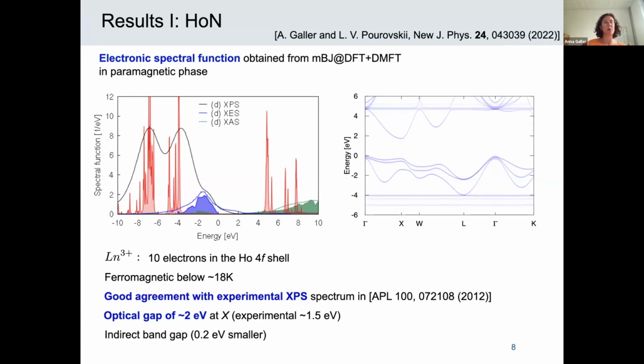So what I can compare here is only the peak position, because in my simulations, I don't really simulate a photoemission experiment, so I don't have any photoemission matrix elements in my simulations. And I should also point out that we also nicely capture this shoulder here. It's seen in experiment, and from our computations, we can say that this shoulder is due to the nitrogen 2p states.